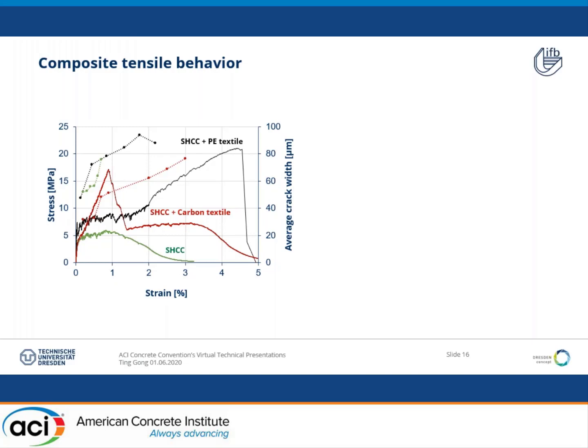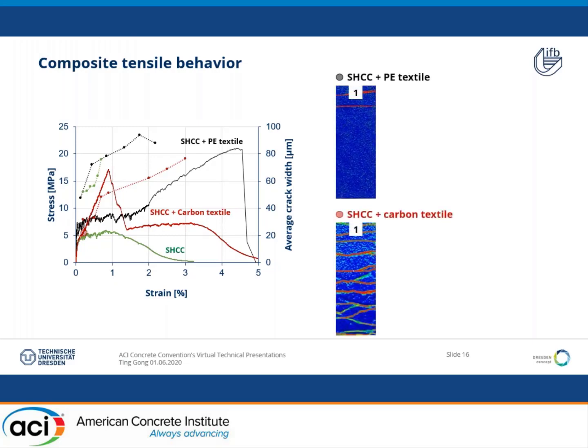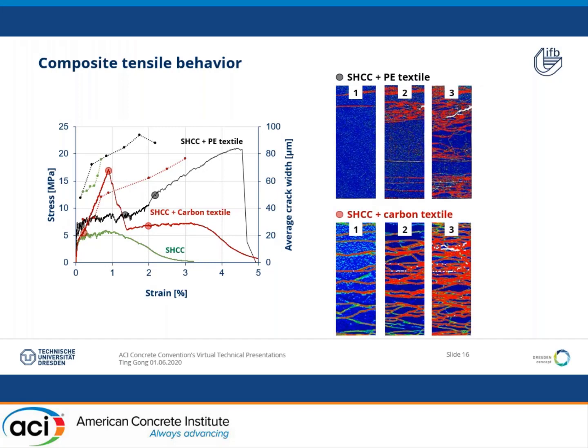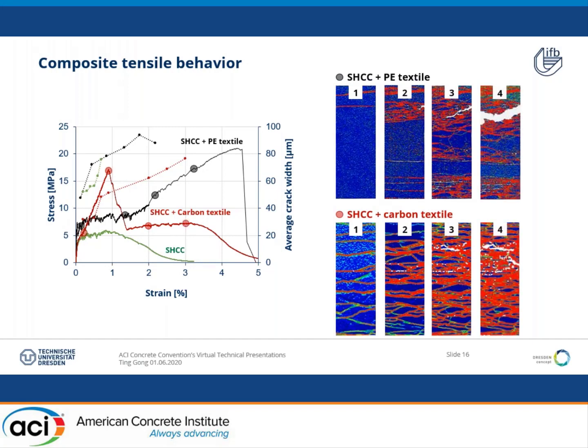An interesting thing that we can observe in the red curve is that the material didn't immediately fail after the rupture of the textile. It means that the carbon textile ruptures sooner than the failure of the short fiber reinforcement. Here we can see the multiple cracking span lasts from the start of the first crack until the ultimate failure of the entire specimen. We should pay attention that this tensile relationship is only specific for this type of material combination, and it is not deliberately designed. So this effect is hardly relevant for real scale scenarios, because failure localization in the strengthening layer would require an extremely severe load input, leading to failure of the strengthening layer, which is not foreseen in this design.